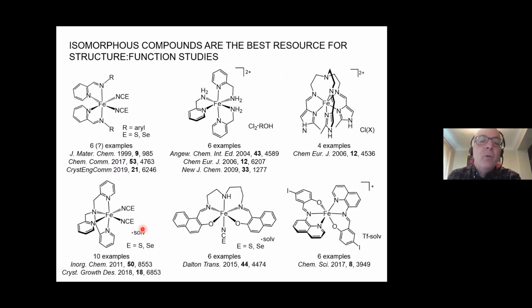And in fact, if you want to understand things like this, what you really need are isomorphous materials, different compounds with the same crystal lattice, the same crystal packing, so that following the scientific method, you can just change one thing in your crystal and show how changing that one thing affects your properties. So if your materials are isomorphous, the lattice is always the same, then you can just change the molecules. So here they're changing the R groups, basically different aromatic substituents here. Or you can change the solvent, which is what Professor Berge did. Or you can change your counter ion, which is what they've done here.